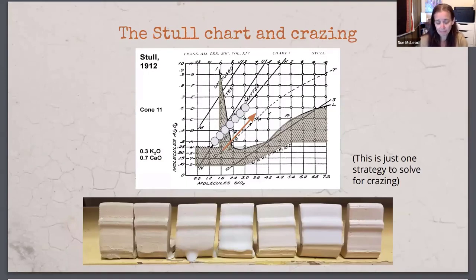So the Stull chart and crazing, this gray region here is where Stull found crazing on his clay body. And this region is not set in stone any more than anything else on this chart is. It can move around. It's just a pattern. And so your glaze might be crazing and not in the crazing region because you're using a different clay body than Stull was using, or you're firing to a different temperature. But basically, if you find your glaze is crazing and it is in the lower region of the Stull chart, then you can add silica and alumina. I recommend adding both silica and alumina, keeping the ratio the same, and you can just move out of the crazing region, and that will lower the thermal expansion of your glaze.